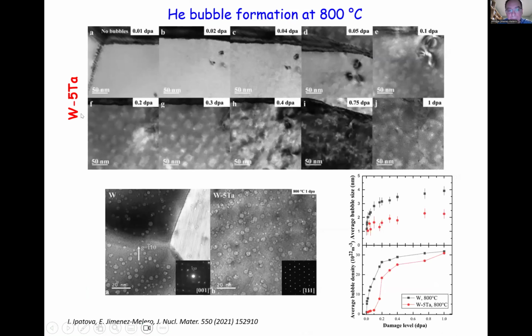We can do the same with tungsten-tantalum, and then you can compare at the end of the process what the situation is, and you can see all these big bubbles. This was done by one of my PhD students, who looked at characterizing the size of the bubbles and how many of them you find. And you see that at the end of the process, at 1 dpa, you reach the same level, but the size is lower when you put a little bit of tantalum, and it also delays the start of the bubble formation. So it doesn't solve the problem, but it delays it a little bit.